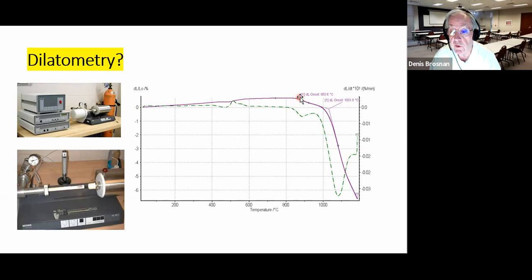And so if we know that point of inflection, sometimes called incipient fusion, if it's a vitrified ceramic, incipient means the beginning of fusion, then we'll start seeing dilation or deflection, shrinkage. Okay, and shrinkage in this particular example begins to take place at a particular temperature indicated up here below 1,000 degrees, between 800 and 1,000. And then we get more rapid shrinkage taking place at an upper temperature just above 1,000 degrees Celsius. And we'll continue shrinking as we continue heating until we get the amount of shrinkage that you want.